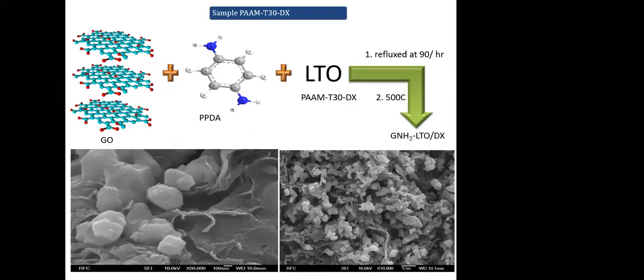Okay, so what we have done in our laboratory, we have modified this lithium titanate with graphene. So we synthesize graphene oxide first, and then with an elastic polymer, along with the PPDA, that para-phenylene diamine based polymer, we incorporate this LTO and did some reactions, and you can see here the LTO particles are fully sitting on the graphene sheet. So you can see that 4% or 5% graphene itself is sufficient for making a good